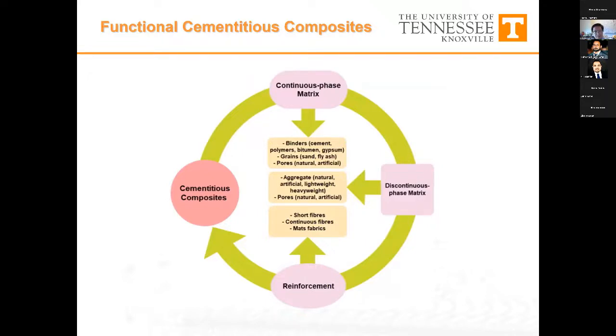majorly three different phases where we have the continuous matrix, which is the hydration product of the binder, right? Whether it's in a Portland cement system or it can be gypsum, polymer, or lime-based binder, and many more. And also we have this discrete phase, which is our aggregates, and sometimes it can be air voids, either naturally occurred or artificially induced, which I'm going to talk a little bit about later. And then from the previous talks, we have heard a lot about reinforcement, different reinforcing strategies in 3D printable concrete that would include short fibers, that's the most common form, and continuous fibers sometimes, and fabrics.